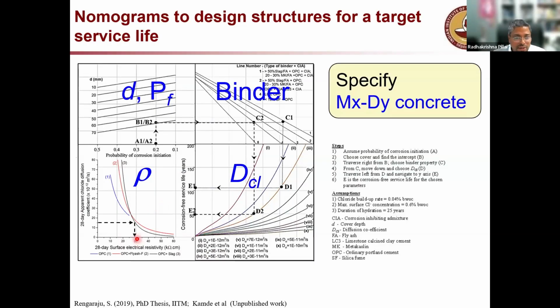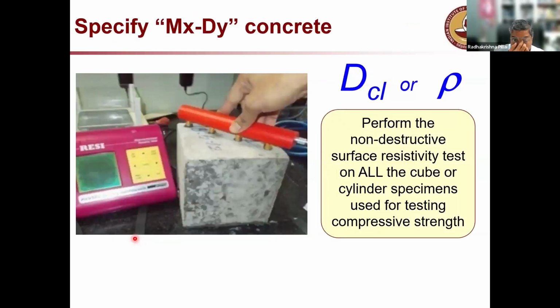I say, for example, in this case, okay, 30 is my target for electrical resistivity. Then my concrete will be good. Now, engineers can do this test on a cube, or even on a structure, and find that, okay, this is the resistivity. So for every concrete compressive strength specimen, when you do testing, you do a resistivity test on that specimen.